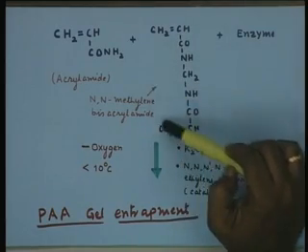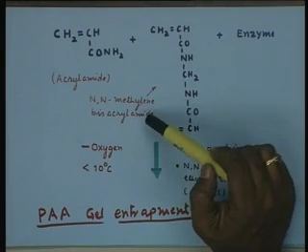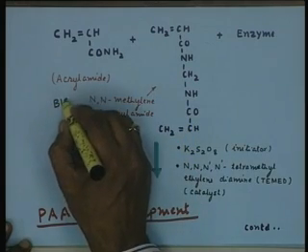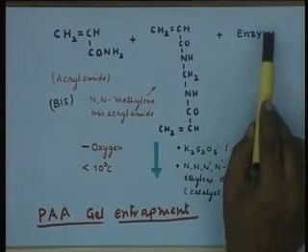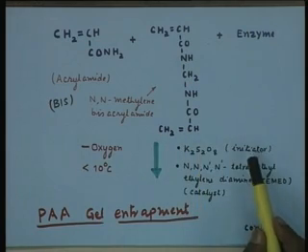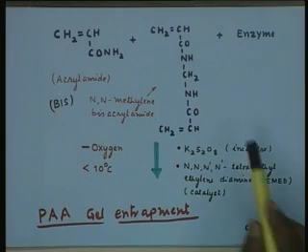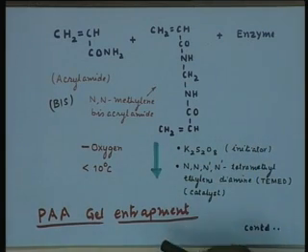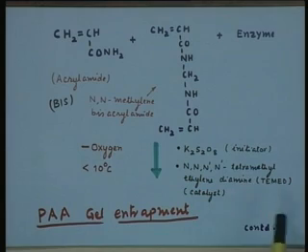The method is very simple in the sense that we start with an acrylamide monomer which is water soluble. To this, a cross-linking reagent, usually N,N-methylene bis acrylamide, often called bis, is added, and then enzyme solution is mixed with it. The 3 water soluble materials are mixed, to which an initiator, potassium persulfate or ammonium persulfate, whatever you can take as initiator, or riboflavin, is added. In fact, a number of initiator molecules can be used. They are initiators. That means it is essentially a free radical polymerization. So, you need an initiator molecule which can initiate the free radical reaction, and then N,N,N',N'-tetramethyl ethylene diamine (TEMED) is used as a catalyst.